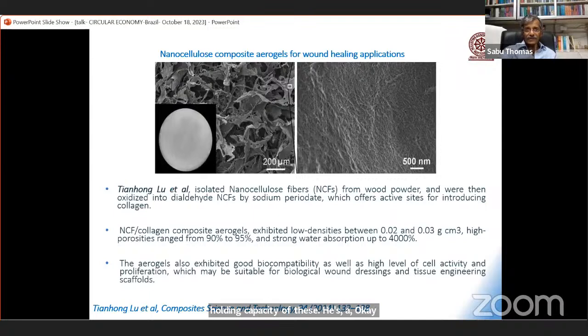And the density of this material is 0.02 to 0.03 gram per cubic centimeter. They're extremely light because they are highly porous. And look at the porosity they have calculated. Tianhong Lu and colleagues tested that these materials are very, very nice because you can absorb all the pus and the water. It becomes very dry, and it is extremely fast. It is an excellent platform for innovation.